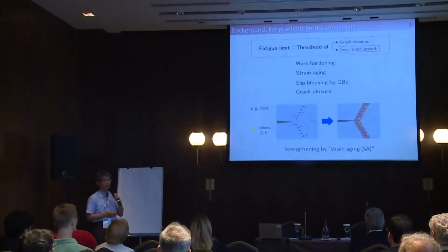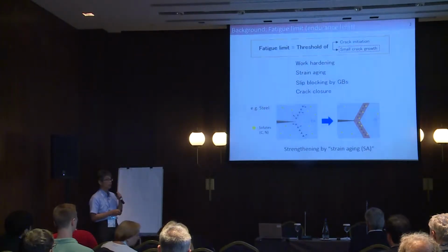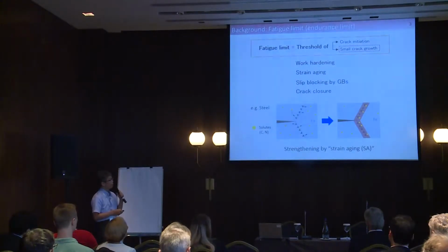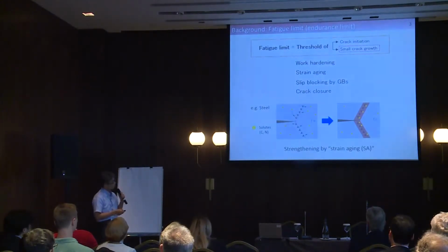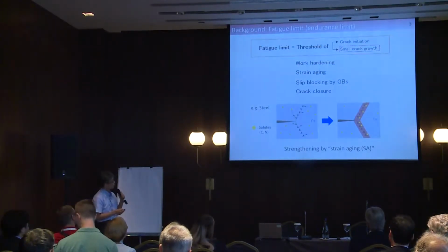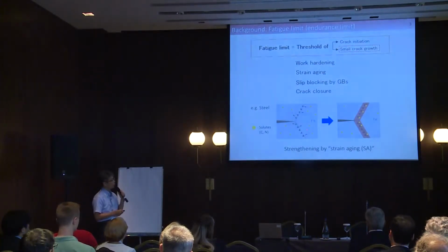The theory of strain aging has been known from the 1960s or even before, probably the oldest one. But this is a very important point. In the theory of strain aging, for example, in steels, solute atoms such as carbon or nitrogen diffuse toward the crack tip and block the slip of dislocations. So if you can apply this concept to an aluminum alloy, then maybe we can make a distinct fatigue limit. And this is very important engineering. This can be applied to a very vast amount of aluminum industry.